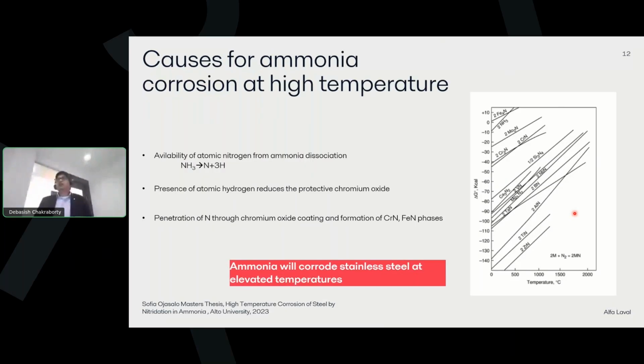And what are the reasons? The main reason is the availability of atomic nitrogen, because a little bit of chromium oxide, or some little bit of exposed metal, dissociates ammonia, and you have atomic nitrogen and hydrogen, which also reduces the protective chromium oxide layer. And as you can see, all the elements that protect stainless steel against corrosion, like chromium, iron, nickel, have quite a high affinity towards nitride formation. So the entire structure disintegrates, and this is something that we cannot really avoid. When the temperature is elevated and you have ammonia, there will be significant corrosion.